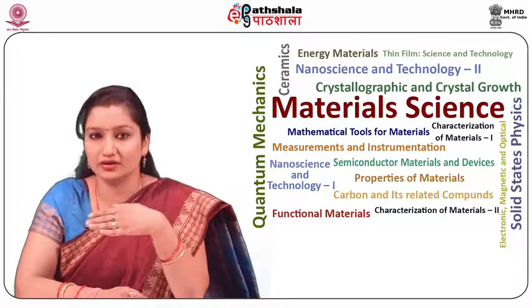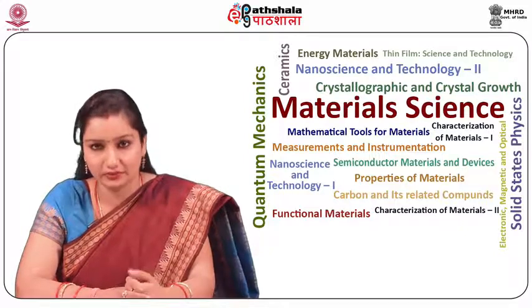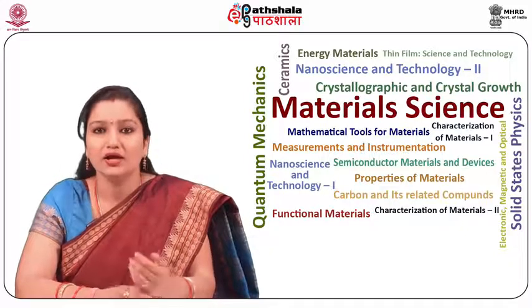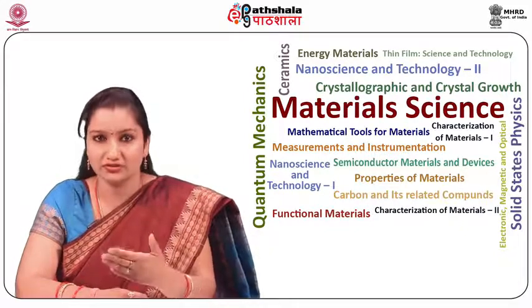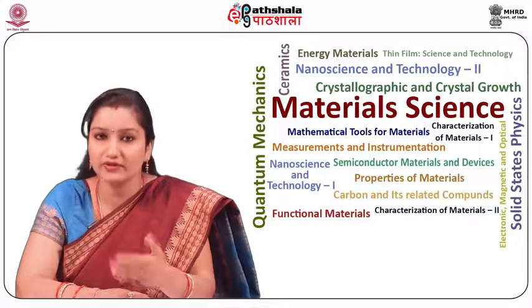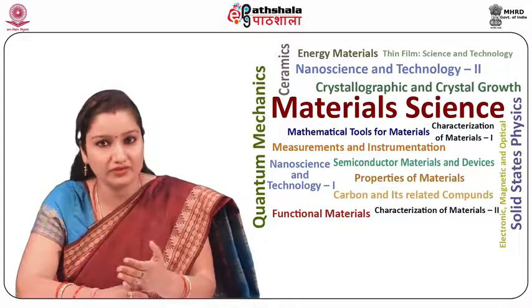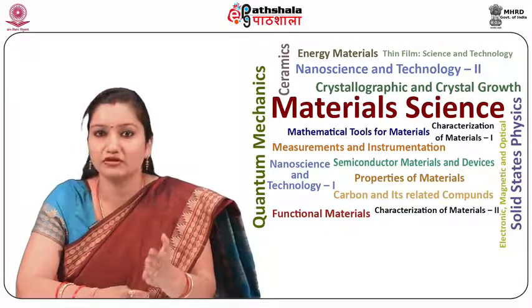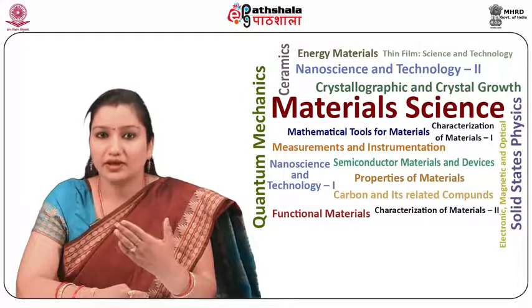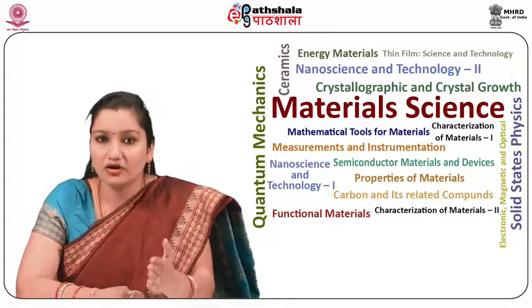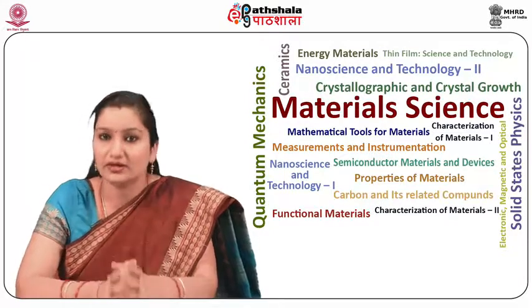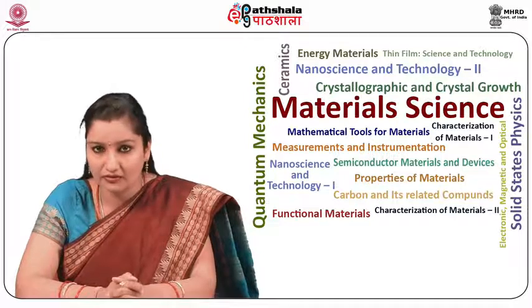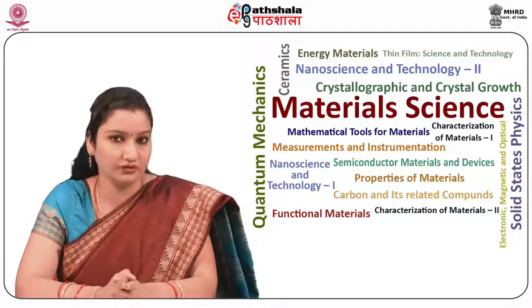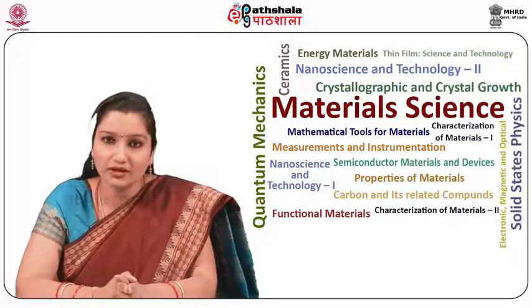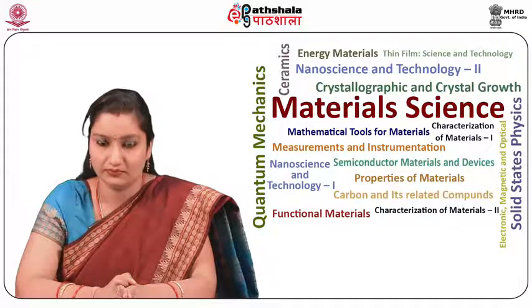The second category is recovery creep, in which at higher temperatures in the range of 0.5 to 0.7 of Tm in K, the influence of work hardening is weakened, and there is a possibility of mechanical recovery.